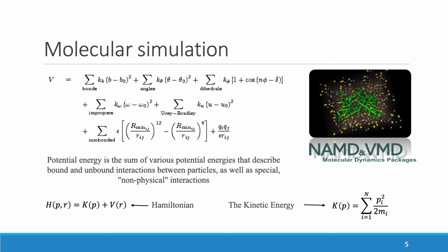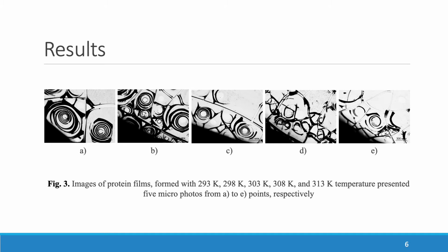All simulations were carried out with a CHARMM27 force field using the nanoscale molecular dynamics package under periodic boundary conditions and a cutoff radius for nonbonded interactions with a switching function starting from 12 angstroms and reaching 0 at 14 angstroms. For these experiments, albumin protein solutions were prepared with a concentration of 5%, since this is the optimal concentration to obtain standard spiral structures. Then the usual drying of experimental samples was carried out at various dehydration temperatures.